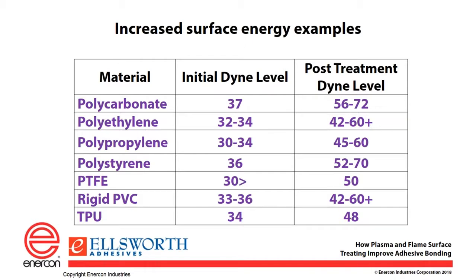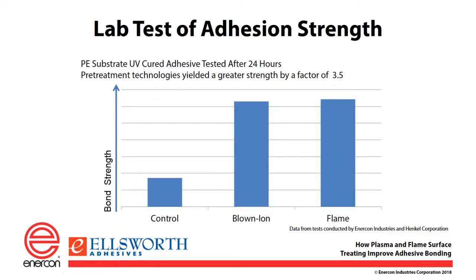Here's some more. Polycarbonate is one of those odd materials that in certain applications you actually get a better bond at a little bit lower Dyne level. And PTFE is always hard to treat. You can get the post-treatment up to about 50, but anytime you have a fluoropolymer, you're going to have issues. The timing of it is such that the treatment doesn't last very long. And we'll discuss that here on the next slide, I believe. Oh, nope, 2 slides, I apologize.